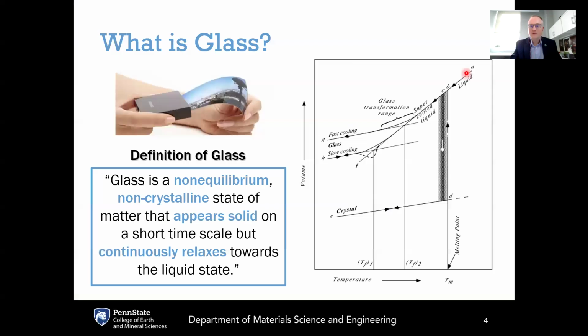So if we start off at high temperatures here in the liquid state around this point A, this would be the equilibrium liquid line at high temperatures. And if you cool the liquid from point A down to point B, the liquid would contract by an amount that corresponds to its thermal expansion coefficient. Now, if you take this liquid and you cool it just a little bit below its freezing point, then there is a thermodynamic driving force for the liquid to crystallize.